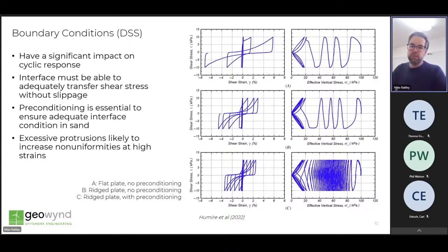So the middle plot shows a ridged platen interface, which provides a more robust transfer of shear stresses to the specimen. So small ridges within the platen, which transfer stress to the soil, but again, without any cyclic preconditioning. But we see with that better shear stress transfer, we get a more resistant cyclic response, i.e. the specimen survives more cycles with lower shear strain accumulations.